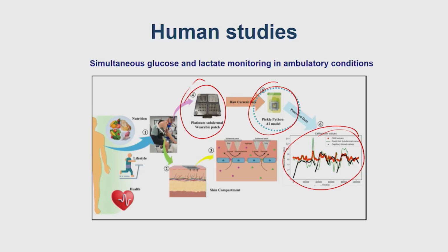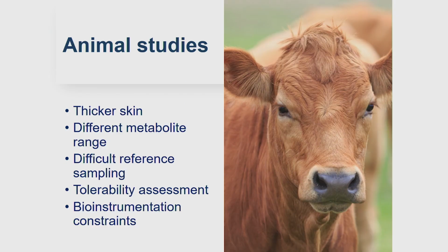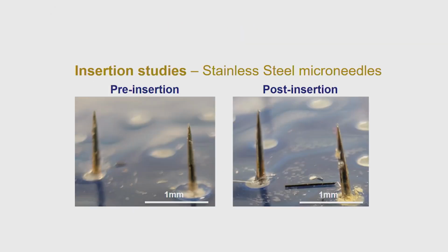And this 20 micron thickness, tip sharpness, that's the standard. It comes from a paper that was published, I think out of one of the institutes in the Netherlands, where they said that anything above the ideal dimensions for the tip sharpness. I mean, it's for animal studies, but still, this tip sharpness that you have here has to be around 20 micrometers.